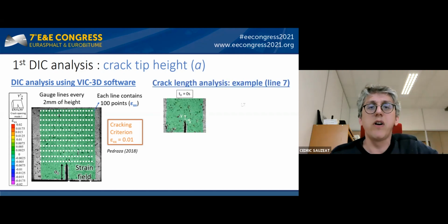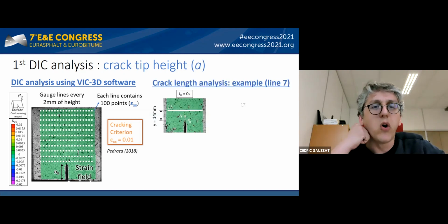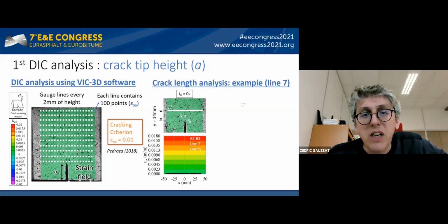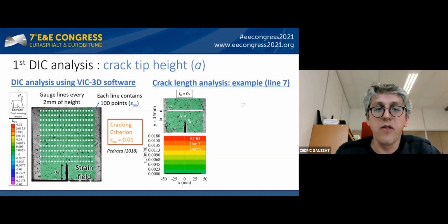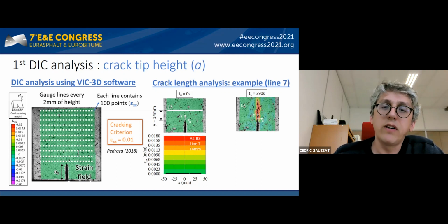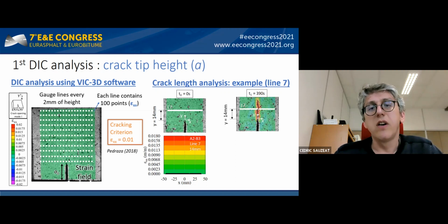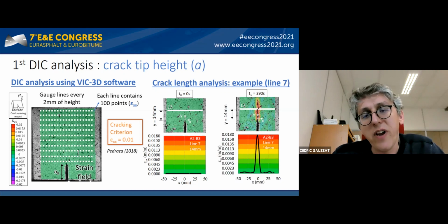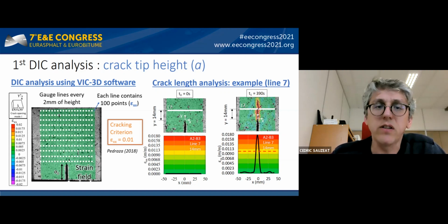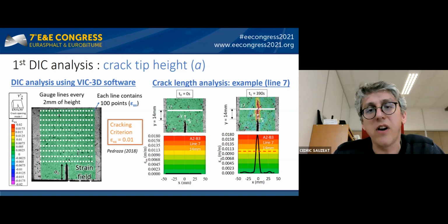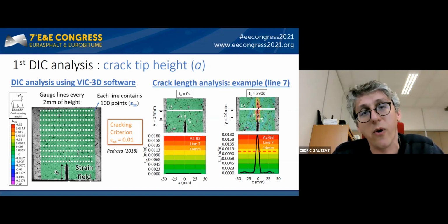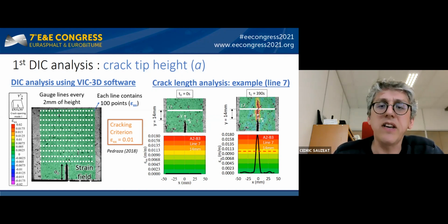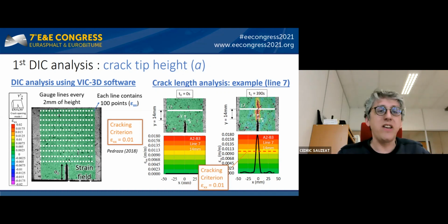I will show you an example for line 7 at time 0. You can see in black at the bottom of the figure the strain along the line, which is very close to 0. And after some time, after crack propagation, you have here the same line and the evolution of the strain along the line. And you can see that the value of 1% was reached in the middle of the line. That means that the crack crossed this line before. A little before. And we can do that for all the lines in the height of the specimen.